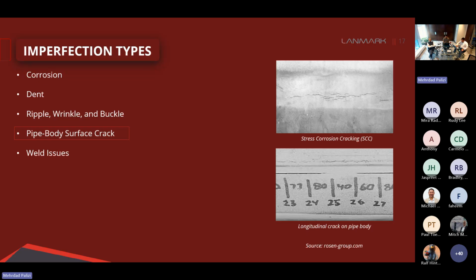Surface cracks over the pipe body. This is another important feature. One common mechanism here is environmentally assisted cracking, particularly stress corrosion cracking or SCC. Here we have tensile stresses. They are working together with a corrosive environment to initiate and grow cracks. SCC often appears as colonies of parallel cracks oriented perpendicular to the dominant stress direction.